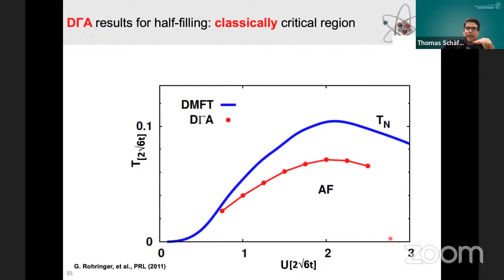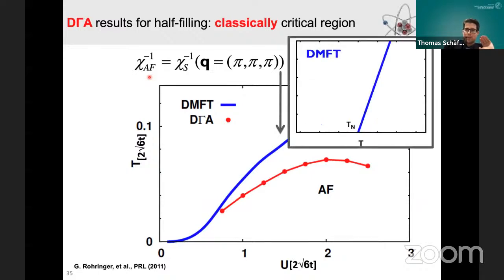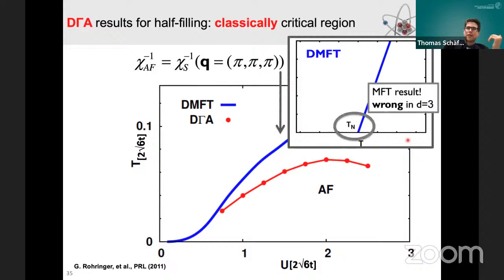We now go into the classical critical regime. Namely, we take a look at the regime close to the phase transition. And we now plot the inverse of this antiferromagnetic susceptibility as a function of temperature. In DMFT, you see, of course, at the Néel temperature, this quantity diverges, which means that the inverse will go to 0. And you see that this quantity is a straight line. And this is actually, in 3 dimensions, a mean field result. This is not correct, because we would expect in 3 dimensions that the Hubbard model, at least at very high interactions, would fall in the same universality class as the Heisenberg model, which does not have this linear behavior.